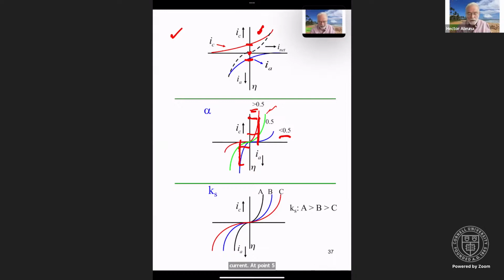And so it gives you a sense for how much the value of alpha affects your current potential profiles, because it tells you what fraction of the free energy change associated with the change in potential goes towards either the reduction or oxidation reaction. Remember, alpha and 1 minus alpha have to add up to 1 for energy conservation. And then finally, we look at the value of Ks in this profile.